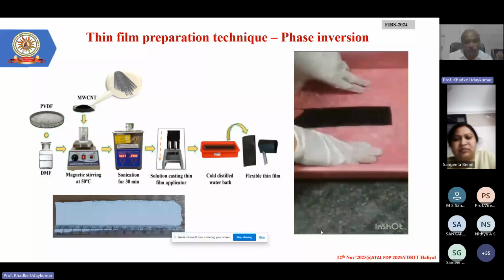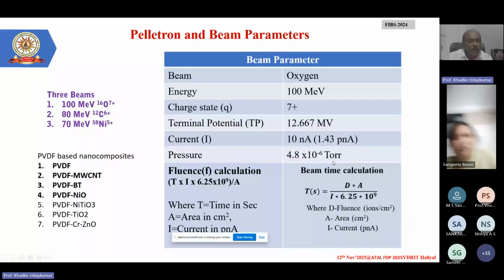So these are the different types of beam we have taken. Three beams have been taken: 100 MeV oxygen beam, 80 MeV carbon beam. In order to have a good amount of conductivity in the PVDF material, carbon beam has been used. For a good amount of dielectric constant in the PVDF, we have used oxygen beam, and a nickel beam has been used so that we can tune the magnetic properties of the material, and those things have been discussed here. I'm just putting what the values are.